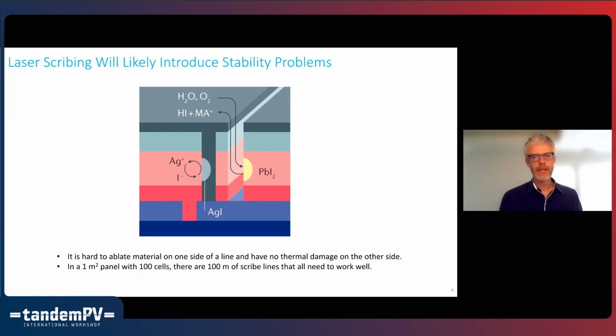And so a lot of times, on the side of the scribe line, there could be some lead iodide, which means the material is degraded to begin with. But I've seen, and I think a lot of people have probably also seen, that once you have lead iodide, it can further catalyze additional degradation. Not to mention, if I were asked to provide just one guideline on how to make these cells stable, I mean, there's more than one guideline, but arguably the most important is do not let metal touch the perovskites, because metals will react with the halogens.